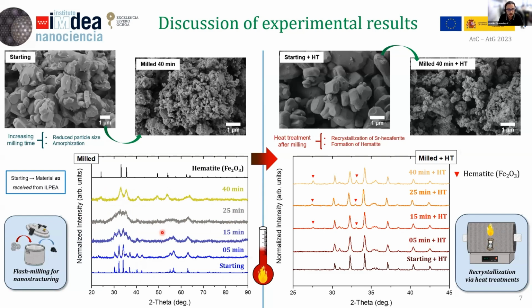So to recover the ferromagnetic phase known as strontium hexaferrite, we apply an optimized recrystallization heat treatment, recovering that way the strontium hexaferrite phase. But we can see here that as we increase the milling time, we induce the formation of the hematite phase.